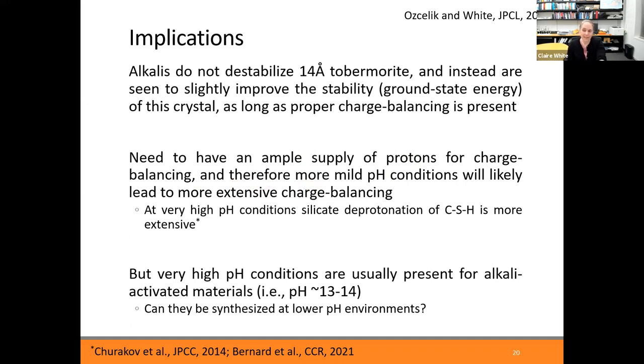However, in concrete, I haven't mentioned this yet, but the pH is quite high internally. It's about 12.5 or 13. The higher the pH, the fewer protons you have, and so you're more unlikely to have this charge balancing occur. So the idea is, could we synthesize concretes using more mild conditions and enhance the stability of these gels? That's something we have yet to look at extensively, but it is an idea for future research from an experimental viewpoint. Are there ways we can catalyze the gel formation in a concrete system without having such high internal pH conditions? So that's the first thing I wanted to talk about today in terms of research.